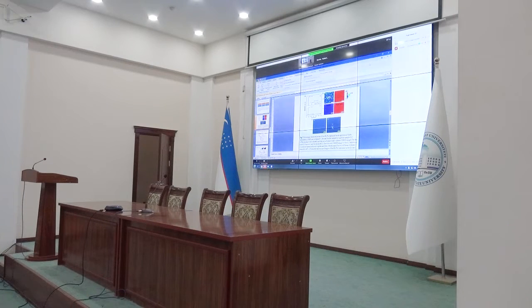Okay, and figure 5c shows the same measured by Nomarski microscope, and on sample L2 this arrow shows the grain boundary between two domains, two crystals rotated by 60 degrees.